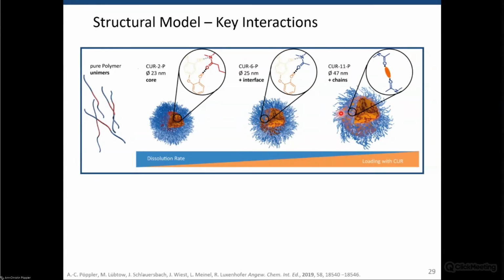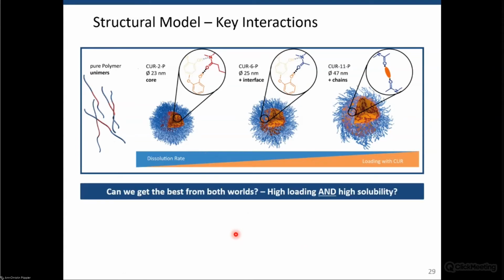And this means you have a competition now of curcumin as a guest molecule with the hydrophilic parts and water with the hydrophilic parts. And this means if water cannot approach these arms anymore, then the arms cannot provide solubility. And this is how we can explain that the increase in loading is making at the same time a decrease in the dissolution rate. And this leaves us to consider whether we have possibilities that we can alter the polymer structure so that in the end we might get something that has a high amount of guest and a high solubility, and this is something that we're currently testing and working on.